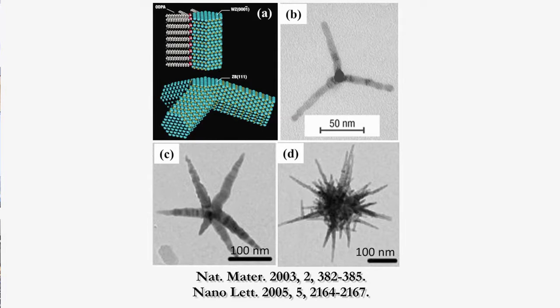For example, for the formation of a three-dimensional branch shape in metal chalcogenide nanocrystals, the nucleation occurs in a zinc blende structure having cubic packing. This nucleating seed terminates into 111 facets having similar lattice spacing to the 002 plane of the wurtzite structure. The anisotropic wurtzite growth extension from these 111 facets of zinc blende creates the final tetrapod or octopod shape, depending on the number of active 111 facets, which can be 4 for the tetrapod or 8 for the octopod.